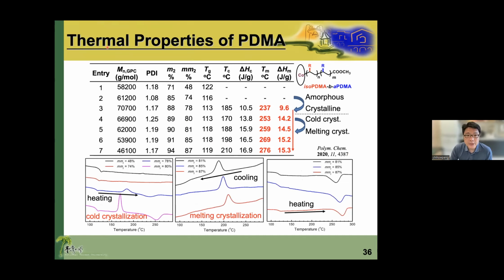So if you compare the thermal property of the polymeric product, we found if you have the tacticity control less than 86%, you obtain only amorphous polymer. So there is no crystalline behavior. However, once the tacticity increased to 88%, we found we can switch the amorphous to crystalline. And if we keep increasing the tacticity control, the crystalline behavior will also change from the cold crystalline to melting crystalline. And you can see the figure here. So the highest value we got is 94% of tacticity control. The Tm approaches the highest, 276, and the crystalline behavior is different. So this is a quite special thing. Then we published it.